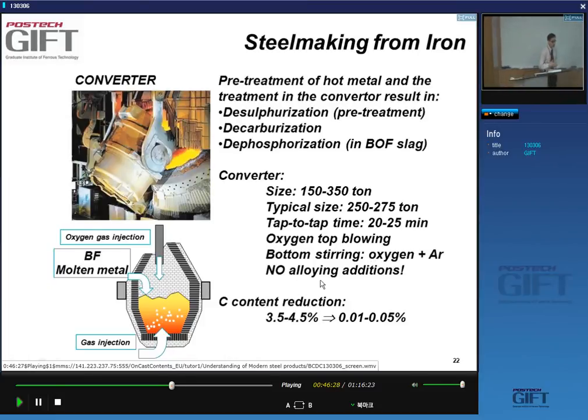And you don't do alloying additions. So the converter is basically just a reactor where you get rid of the carbon. The original carbon is about 3.5 to 4.5% and is reduced by a factor of about 100 to 0.01 to 0.05%. In this course, when I refer to percent in compositions, I mean weight or mass percents, not molecular or atom percents, which some people in physical metallurgy will use.